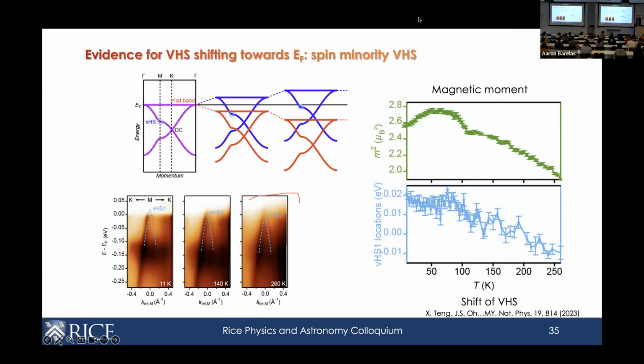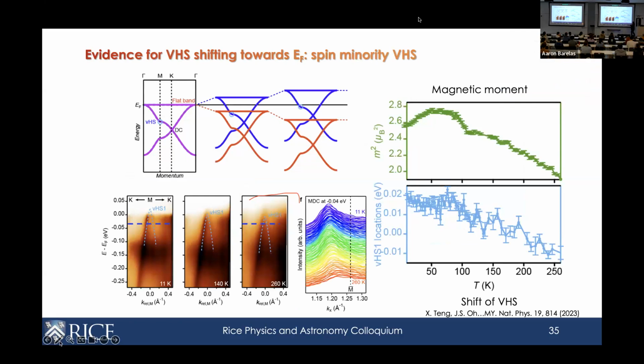And also, we have done temperature-dependent evolution of this. We can measure the Van Hove point as a function of temperature. We can see that it shifts as expected across temperature. And this is the shift of the band. And this is the ordering of the moment. We can see that this picture is at least to the zeroth order qualitatively correct. Okay. And just to show the ones that want to see the actual curves, we have done very fine temperature dependence. You can see this peak is where this band is as a function of temperature that shifts towards the